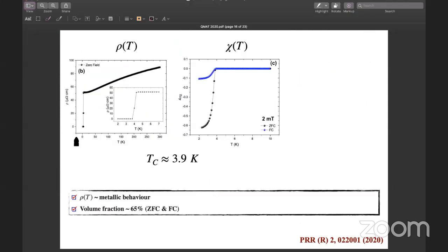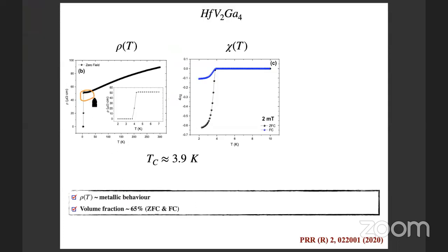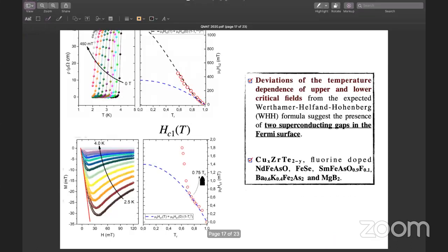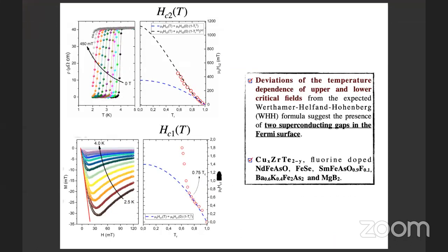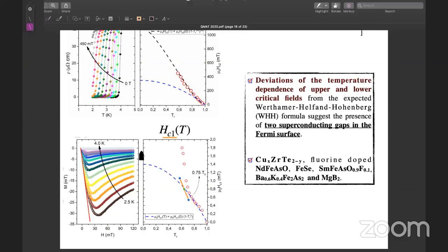Okay, so you can see from the resistivity data, we have a sharp drop at 3.9 Kelvin, and the superconducting volume fraction is found to be around 65% at 2.5 Kelvin. Also, resistivity shows linear behavior, meaning metallic behavior. The interesting point we observed is that the lower critical field value significantly deviates from the BCS signatures, as you can see in this graph. So this motivates us to investigate this material using MuSR.